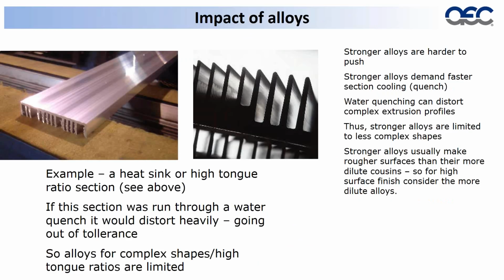Now here, you have a picture of a heat sink, 2 heat sinks in fact. And there are 2 elements to this. The first thing is the length of the legs. Try to imagine the steel die, which is the exact opposite of this image. There are long steel tongues with almost no support under enormous pressure. So making these dies is challenging. Imagine running those through water, you'd have all sorts of problems. Those legs would deform and it would just not work. So for alloys with complex shapes and high tongue ratios, our choice of alloys are really quite limited.